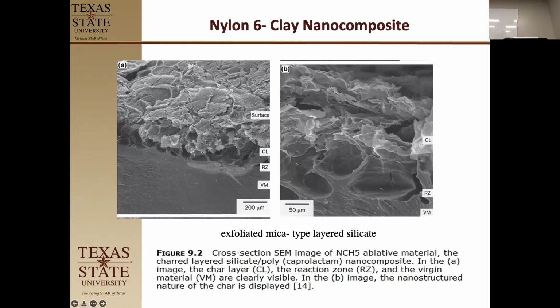So right here, this is the result of using montmorillonite clay in the nylon 6. That's a ring-opening nylon, it only has one functional group here. And they clearly show this is the surface of it here. This is the char zone. See how it's kind of a foamy area? Then this is the reaction zone, or the pyrolysis zone, or the decomposition zone. So it's changing in its color and density compared to the virgin material. This is still mostly solid, but it's starting to get porous. This is highly porous. And then the surface has actually been ablated.